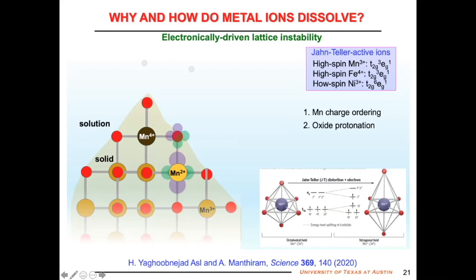Once it becomes like that, the trace amount of proton present in the material can protonate the oxide and water can be formed, and that can go away along with manganese. So that's how the manganese 2+ goes into solution, and then the dissolved manganese goes to the anode and causes all these problems.